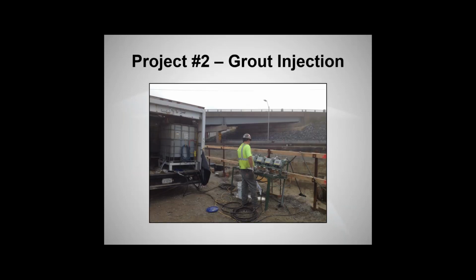So a picture, this was later in the program. Most of the grouting had been done. This was to go back and do a little extra grouting. But just to show sort of the equipment, the setup, here's a plant that's going to do a solution grout. You can see there's mixing tanks here, so there would be an A side and a B side with a pump in the middle that pumped a 1-to-1 ratio out into a mixing head before it went through flow meters. This plant would be set up to inject 4 holes at a time. There's 4 hole meters or 4 flow meters here. It's important for permeation grouting typically. Since you're pumping at low injection rates, you want to be able to pump multiple holes at one time to make the grouting efficient. So that's sort of what this is showing.